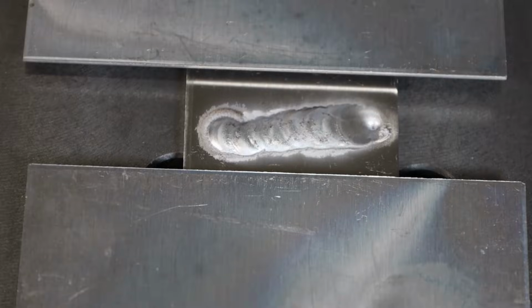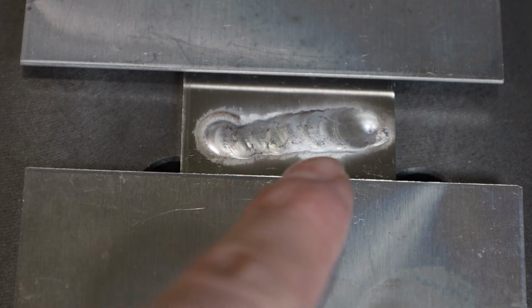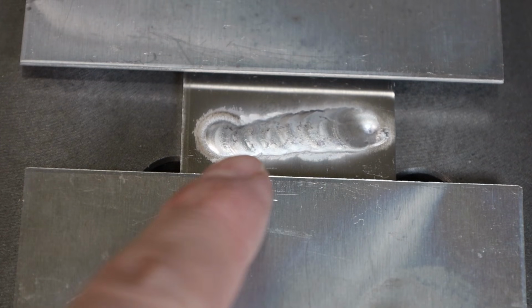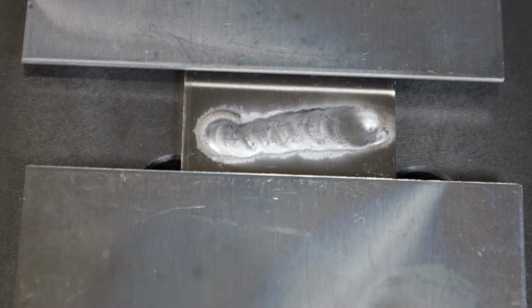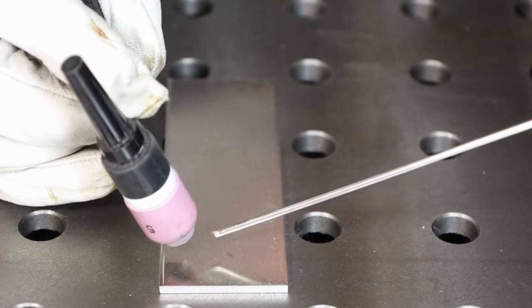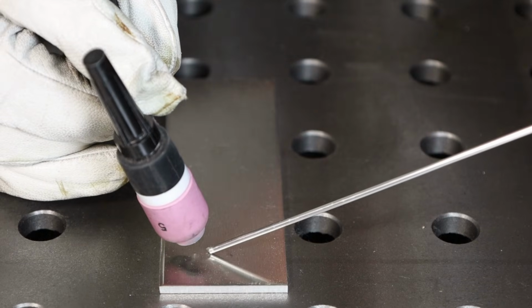Because the filler metal is getting contaminated and oxidized before it goes in, and it's taking all that junk into your weld pool, and we don't want that. And so if you're struggling with that, there are 3 things to correct it. 1, make sure that your arc length isn't too long, because that will make it more difficult because you have that large weld plume, right, that cone coming off. 2, make sure you don't have way too much torch angle, because that won't help either for the same reason. And 3, make sure you get your filler metal in and out of the leading edge of the weld pool quickly.